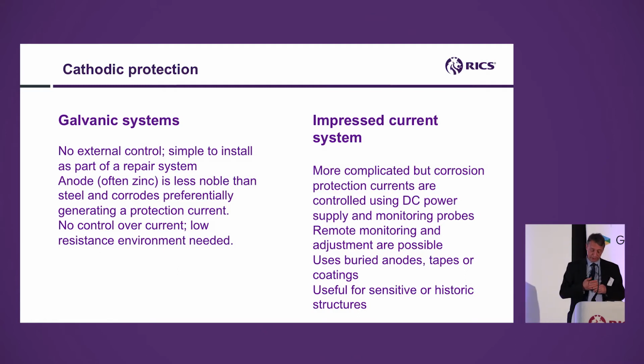The other is an impressed current system where you put some anodes in. That could be a mesh, it could be a paint, it could be little probes that you insert and connect up to a DC current. You put a current through the whole thing, and that reverses the corrosion currents that are occurring in the steel. A useful means, because you don't necessarily have to open up all of the chloride-affected concrete, or stonework for that matter, and hoik out those areas that are vulnerable to decay. So it's a great technique, and one that is gaining in popularity. It sounds a bit sci-fi, but it's quite straightforward, really.